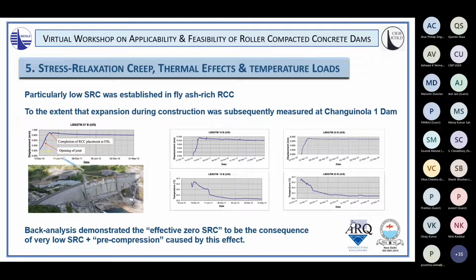And back analysis demonstrated the effective zero stress relaxation creep that was seen in these arch dams is actually a consequence of, first of all, very low stress relaxation creep and this pre-compression effect with the actual arch crest getting longer. So it's a combination of these two things, low stress relaxation creep and this pre-compression of the crest getting longer as it's being built. And in fact, that only happens because of the low stress relaxation creep. So as the structure becomes more flexible with height, its containment of the thermal expansion is less, and therefore it is actually physically able to expand. So because of the low stress relaxation creep, you get this combination of two things that give us this overall effect of zero stress relaxation creep.